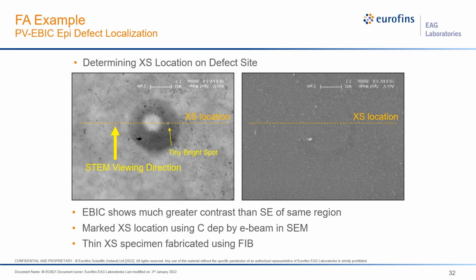There is some indication of this feature in the secondary electron image here on the right. And it looks like there may be a pit here, so there's a little dark spot that maybe corresponds to this bright spot here. So what we've done and what we can do is we mark this cross-section location very carefully in the SEM, and then we use the dual beam to lift it out in situ and image this in the scanning transmission electron microscope.